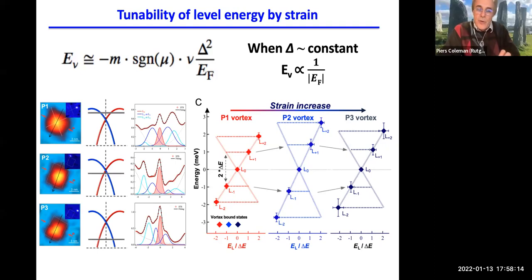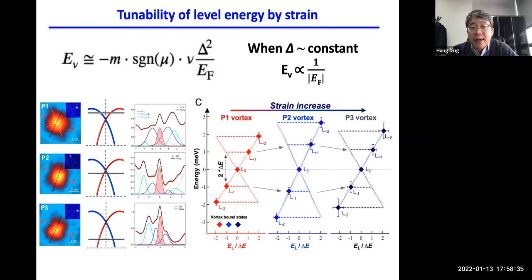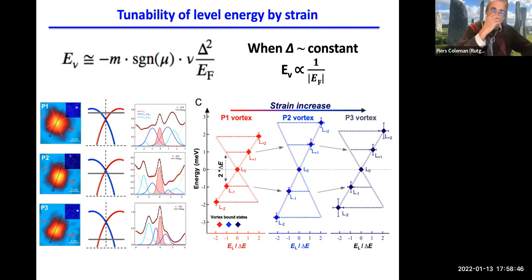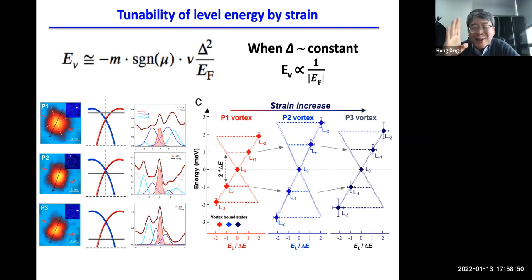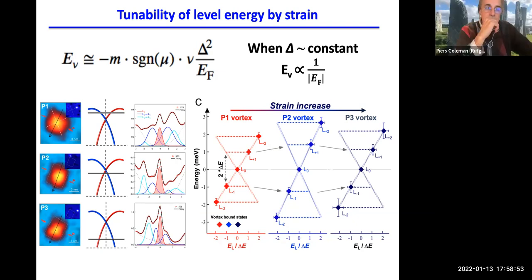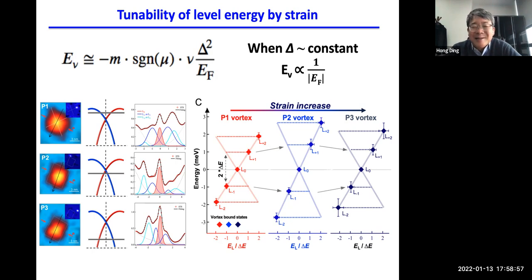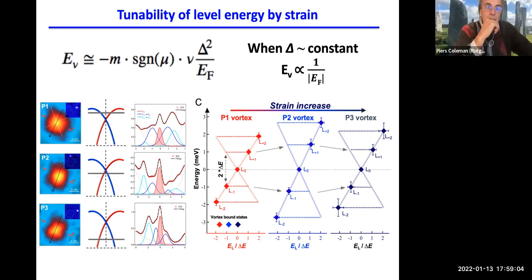And just to clarify, you're thinking of this in terms of a topological picture, in the same way as Liang Fu's original picture. You're thinking that you've got a topological surface state interacting with a bulk, shall we say, S wave or S plus minus wave superconductor. Is that your picture? Yes. We have this Dirac surface state, which will become a superconductor. We demonstrate that the superconducting gap is actually slightly smaller than the bulk, which shows this is an induced superconducting gap.